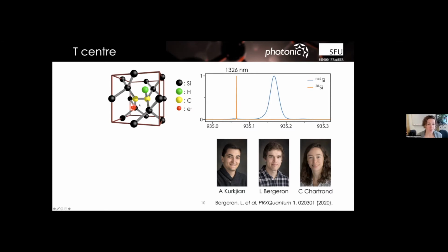There was a suggestion put forward that there was an unpaired electron spin in the ground state. It wasn't actually resolved in the literature before we got started whether that was true or not. There were conflicting reports in the literature as to whether or not it had an unpaired ground state electron, and it does, which is great. So we took a look at it in silicon-28. We followed the older recipes, and you can compare the natural silicon inhomogeneous distribution to the silicon-28. It goes through this dramatic narrowing again, which is phenomenal.